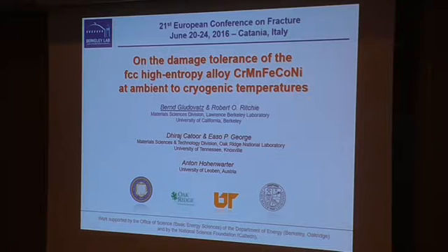Again, we had an equiatomic single-phase material, equiaxed grains, also numerous recrystallization twins. The elastic properties were measured using resonant ultrasound spectroscopy in the range from room temperature down to liquid nitrogen temperatures and were found to be about 200 to 250 GPa, and the Poisson's ratio was about 0.26 to 0.27.